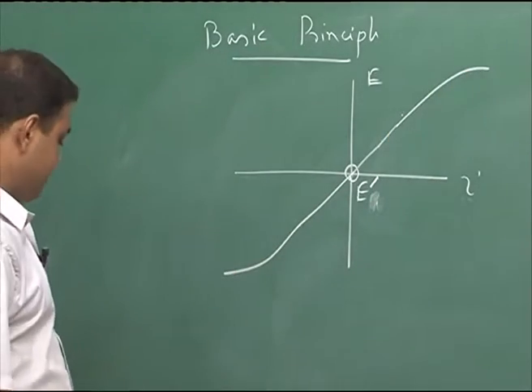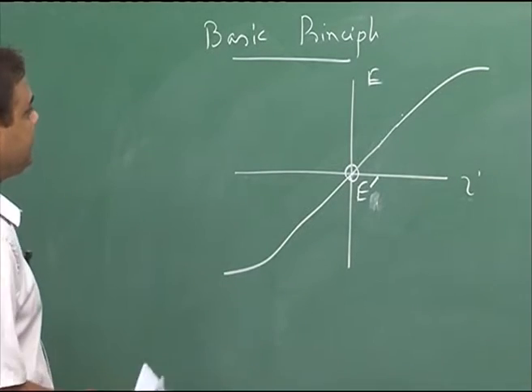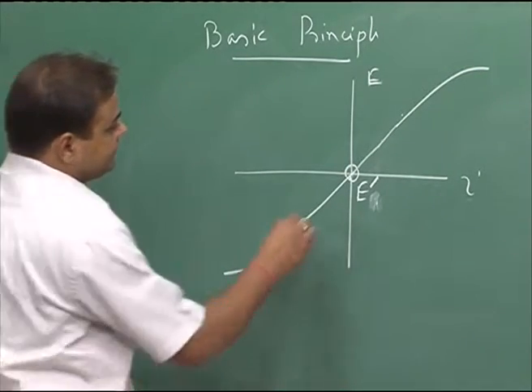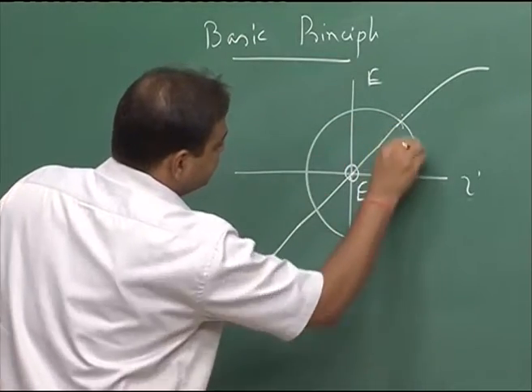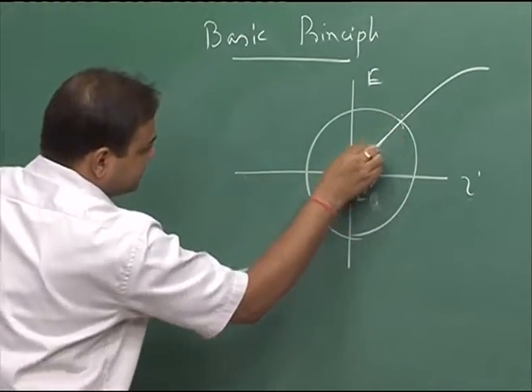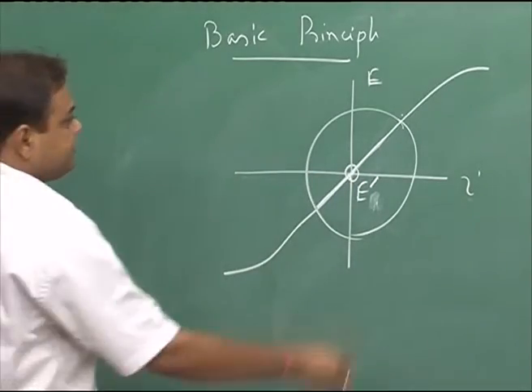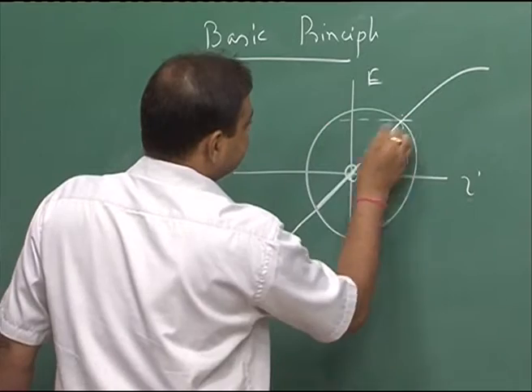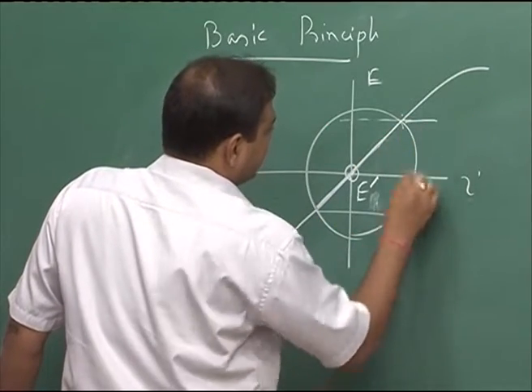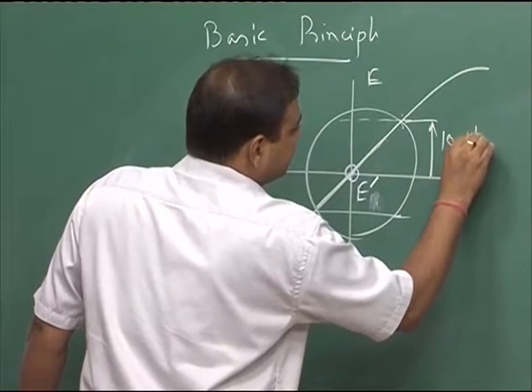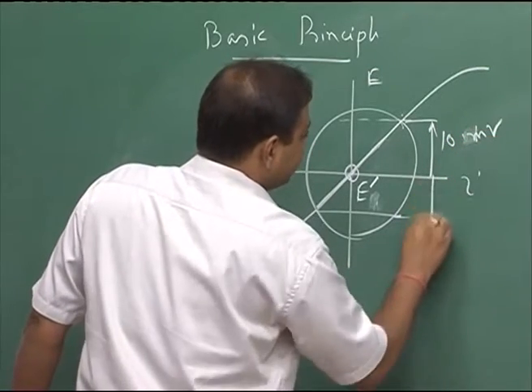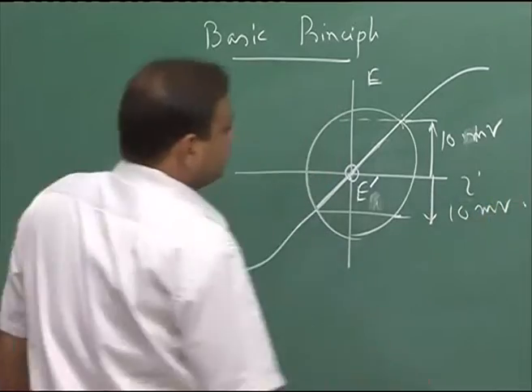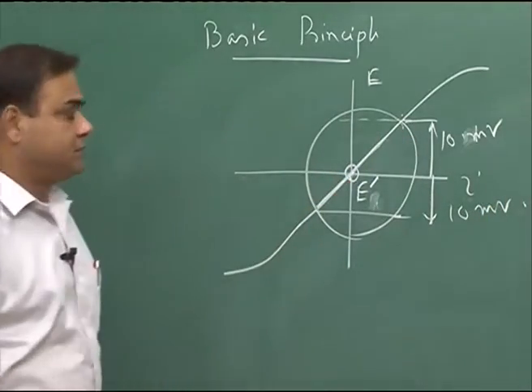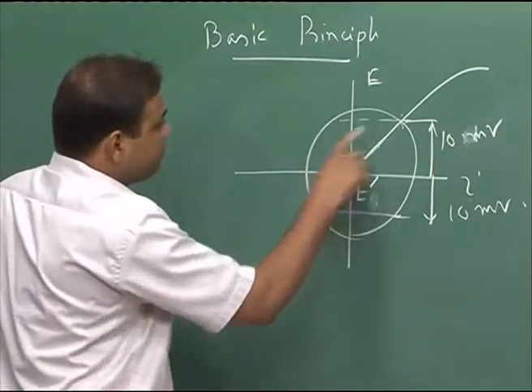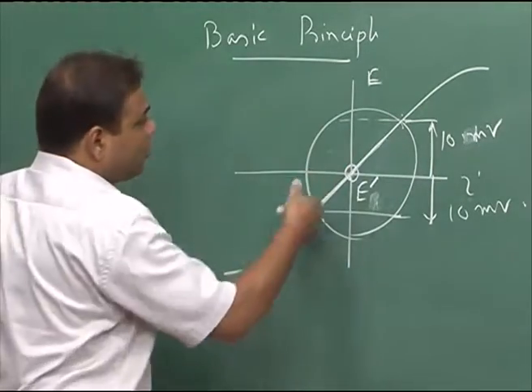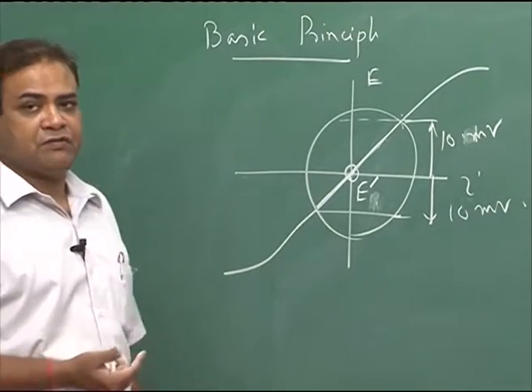The graph would be like this. So, if we have this graph, then we say there is a very small region where this line is linear. This is the voltage where this part is linear, around 10 millivolt on each side. So in this region it is linear, and from this linearity the slope can give us the indication of corrosion rate.